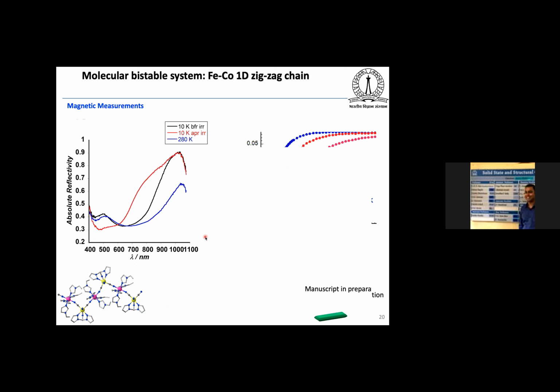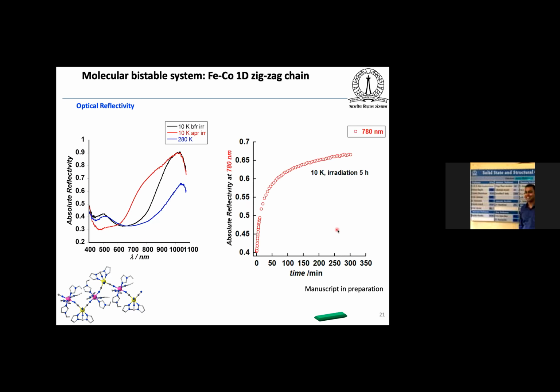But what is happening when we perform the optical reflectivity measurements at different temperatures? So you can see the blue curve is 280 Kelvin, the red curve is 10 Kelvin after irradiation, and the black curve is 10 Kelvin before irradiation. You can see there is a huge change, particularly in this 500 nanometer region, and also the 750 to 800 nanometer region. There is a huge change between before and after light irradiation of the systems. We irradiate the systems at 10 Kelvin using white light, and we plot the absolute reflectivity at 780 nanometer.